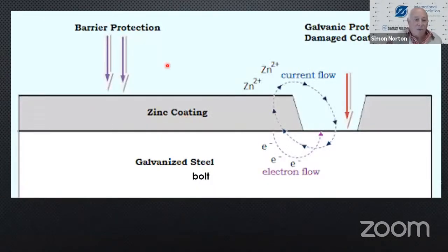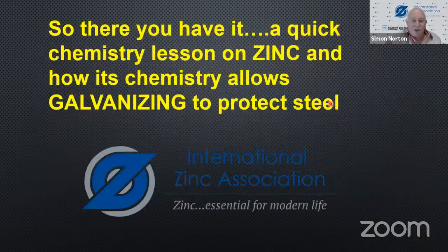So in summary, we've got zinc acting as a barrier and acting electrochemically to protect your galvanized steel or your galvanized bolt. The zinc is oxidized into the solution. The damage here is protected galvanically. So you've got a physical barrier, a galvanic barrier, and the corrosion products of zinc also fill up these sort of gaps. So you've got a multi-layered protection when you work with zinc. So there you have it, a quick chemistry lesson on zinc and how its chemistry allows galvanizing to protect steel.